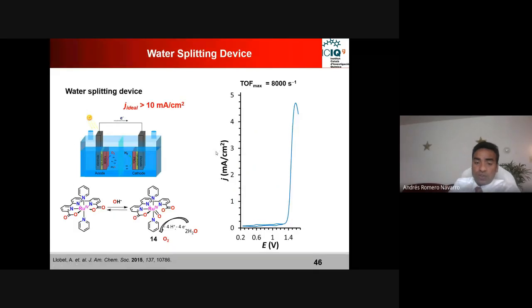And so as I was saying, our desire is to design a water splitting device. It's not just a homogeneous molecular catalyst. For a water splitting catalyst device, we always have this target to achieve a current density above 10 milliamp per centimeter squared. So can we do that? We thought, okay, this molecular catalyst is a very good one. It's showing very good catalytic activity with a turnover frequency above 8,000 per second. So this is the fastest molecular catalyst reported in the literature so far.